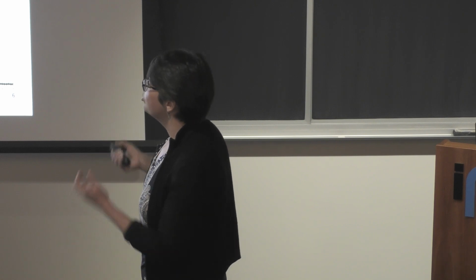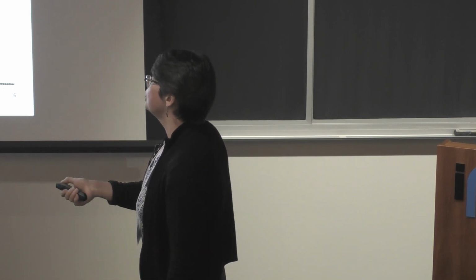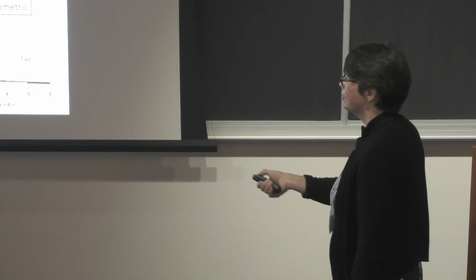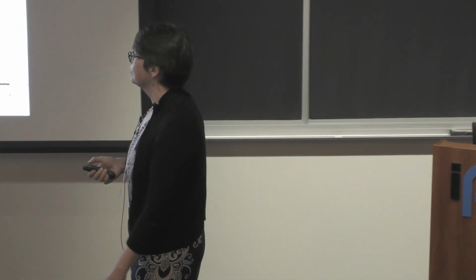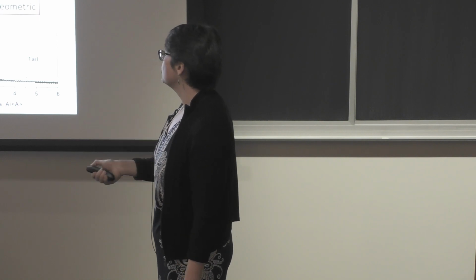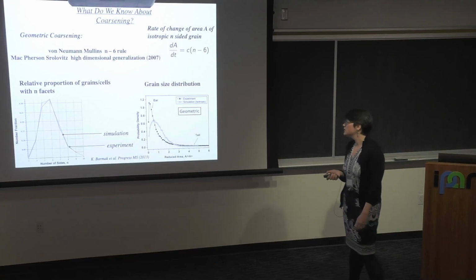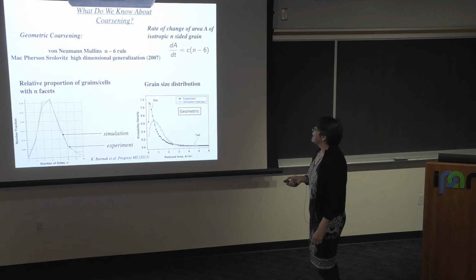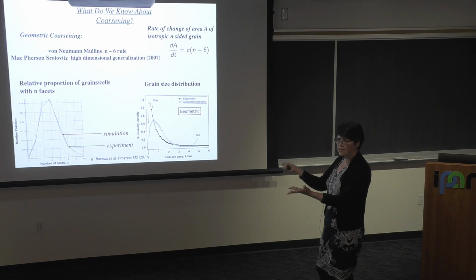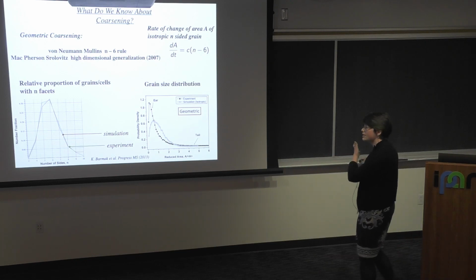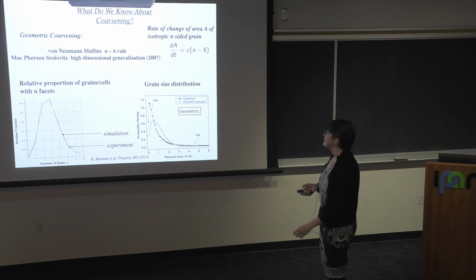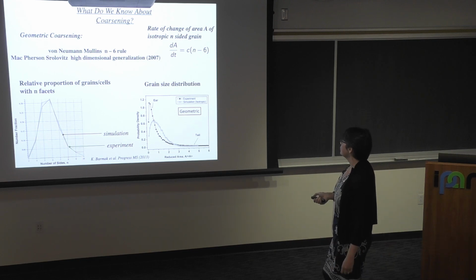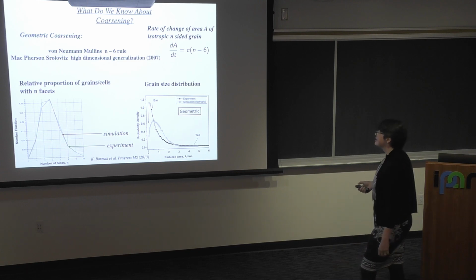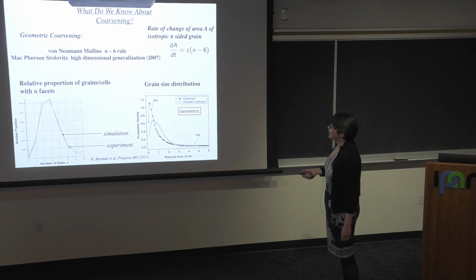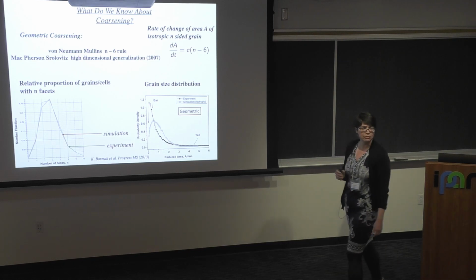For example, it is important for material properties to understand the distribution of grains with a given number of sides. And here, our simulations and experiments are actually in good agreement. They're doing pretty well here. The other important metric is the grain size distribution. For example, we know electrical resistivity depends on grain size. Unfortunately, here our numerical simulations and experiments are not doing as well. The disagreement is in the range of very small and very large grains.